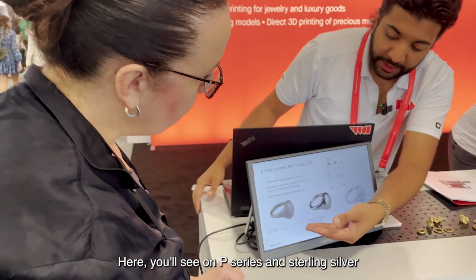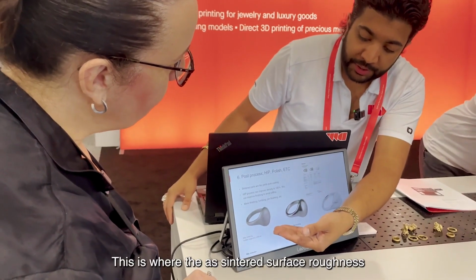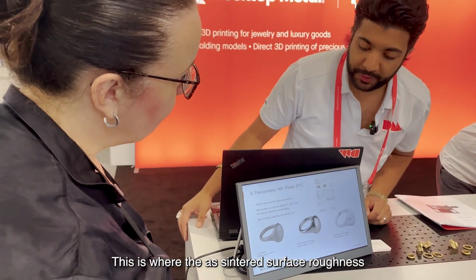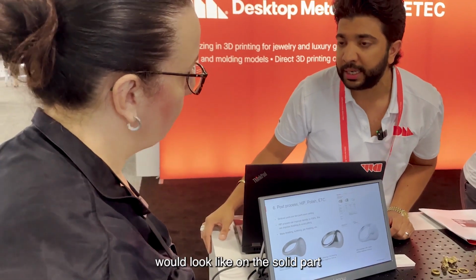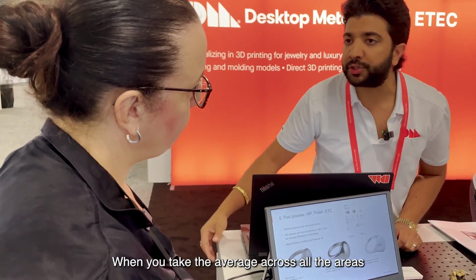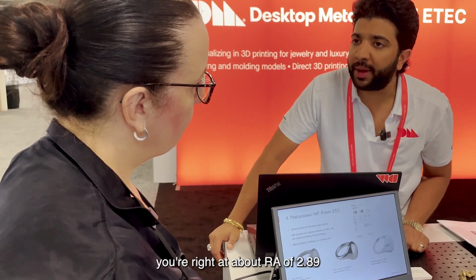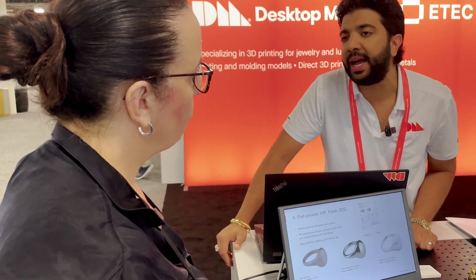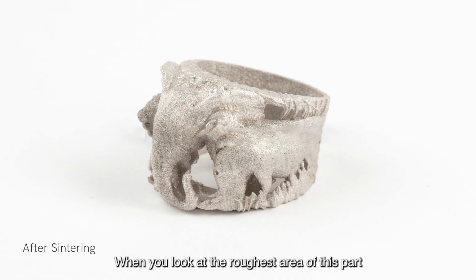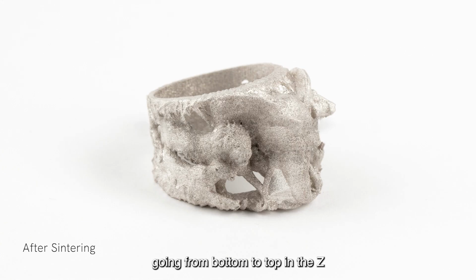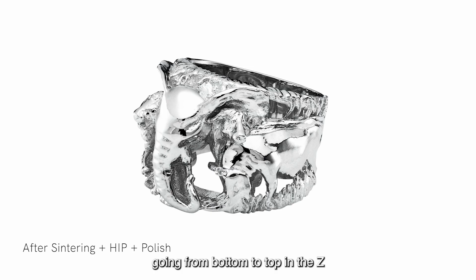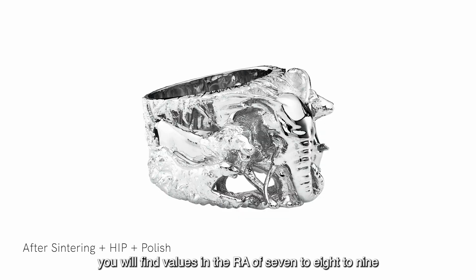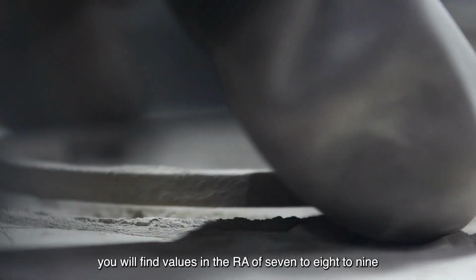An average across the axes, here you'll see on P-series and sterling silver, this is what an as-sintered surface roughness would look like on a solid part. When you take the average across all the areas, you're right at about an Ra of 2.89. When you look at the roughest area of this part, going from bottom to top in the Z, you will find values in the Ra of 7 to 8 to 9.